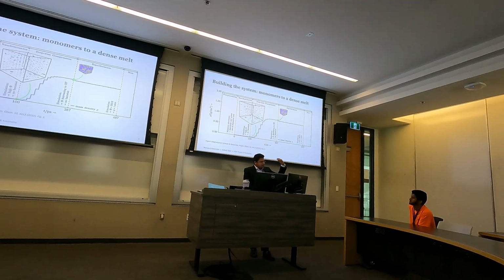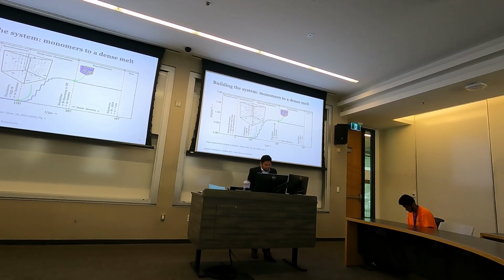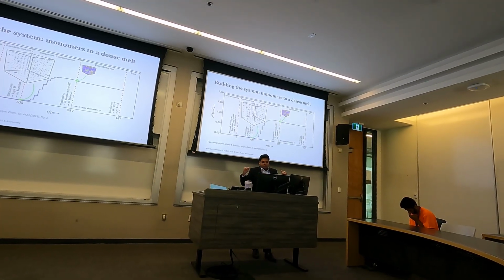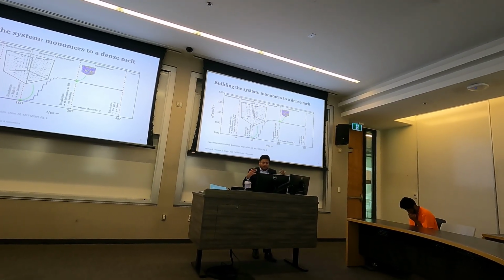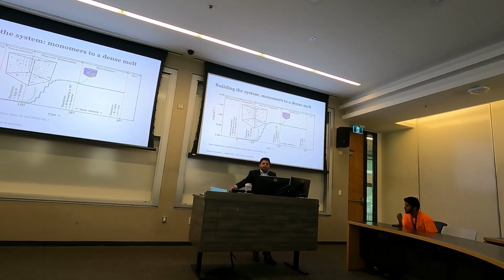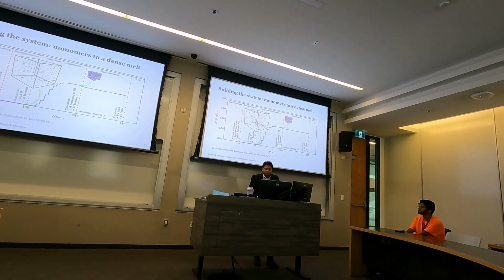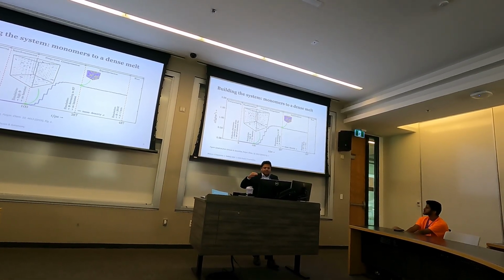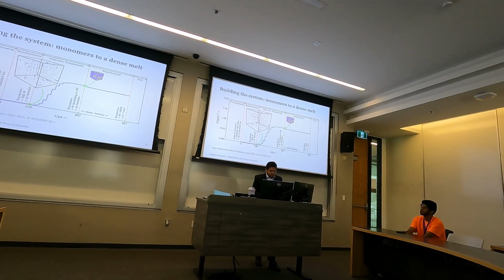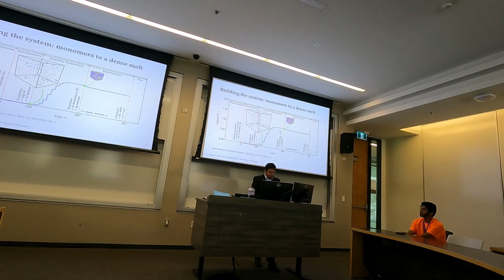Once we reach a density a little higher than the experimental value for this uncured polymer, we equilibrate it for a very long duration in an NPT ensemble, where we keep the temperature at 290 Kelvin and the pressure at 1 atmosphere. The system equilibrates automatically, and the density comes back to the experimental value of around 1.08 grams per cc.